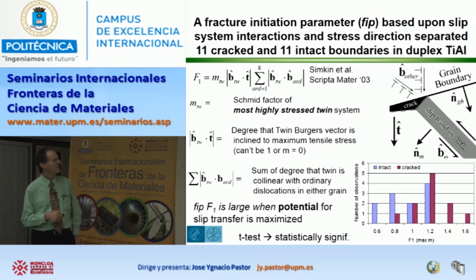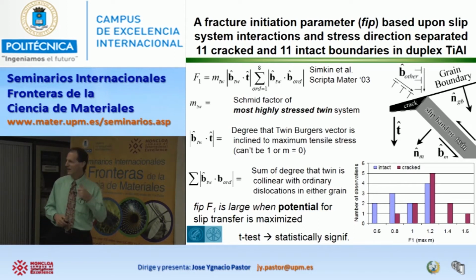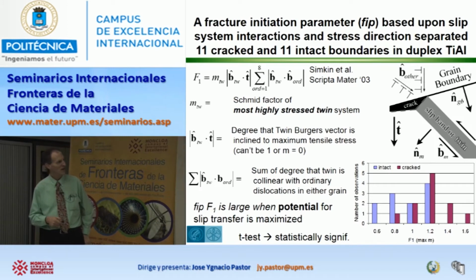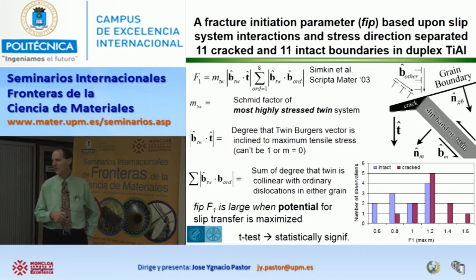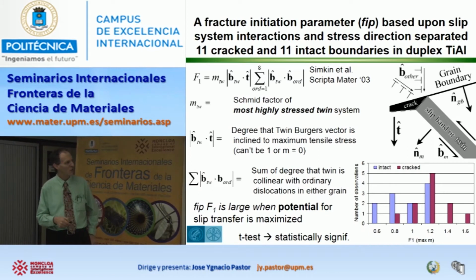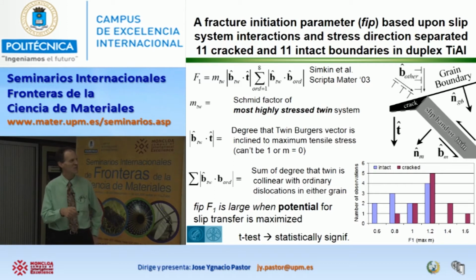So our idea is that if we have a parameter that can tell us whether the potential for cracking is high or low, then we can say, well, I just described to you that a mechanical twin here can sometimes generate a crack at the grain boundary. Now, a mechanical twin has a strong sense of shear. It's very concentrated shear. So if you think about atoms moving down on this side and up on that side, we develop a big opening tensile force at the grain boundary right where this twin is. And if we don't have dislocations on the other side of the grain boundary that can feed material into where the crack is going, then the crack is likely to happen. And so that's what this is basically saying.